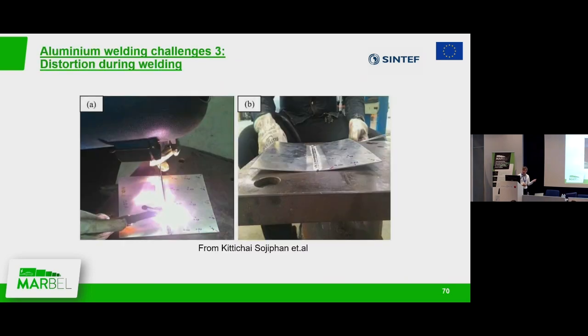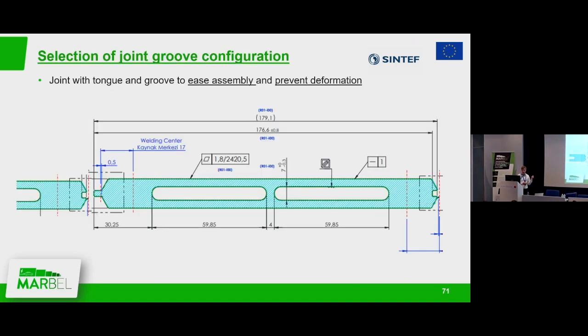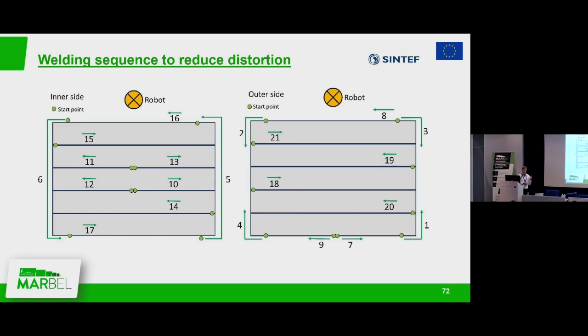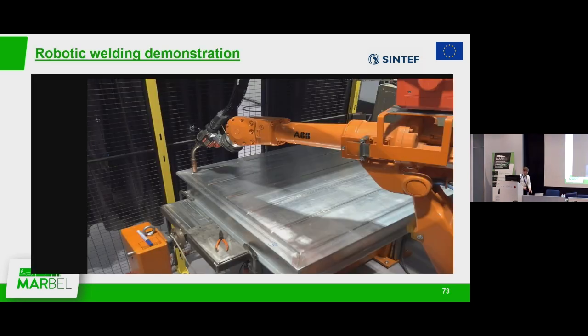The third problem, which is rather important as well, is distortions during welding. Aluminium distorts much more than steel because of the thermal expansion and also thermal dissipation. So here we design a tongue and groove which connects each other in the assembly, which makes the assembly easy and prevents deformation to a large extent. However, we also have to develop welding sequences that reduce the deformation by reducing the heat input into the aluminium.